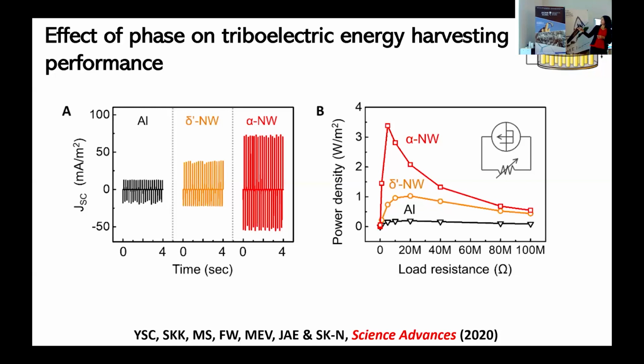We've done this using aluminum instead of the nanowires, and then our delta prime nanowires and alpha nanowires. And what we're looking at is the current density that you get as you excite this device. And if you look at the power density, at the end of the day, we want this to do some work. So if you have a bunch of resistors across which you're trying to dissipate the power, then the highest power output you get is for the alpha nanowires.